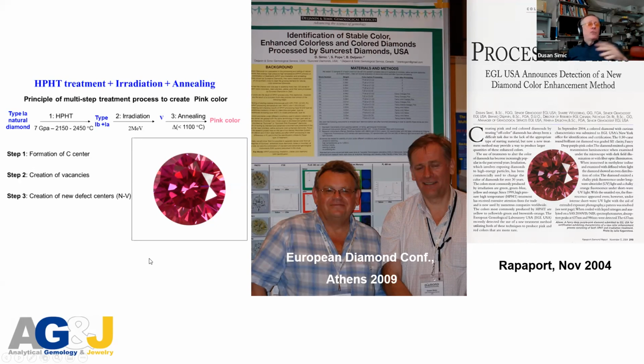I'm sure that you know all about this, but just to repeat first: you have to deassociate nitrogen to create single nitrogen. After that, make irradiation, and during the annealing, this single nitrogen will be bonded with a vacancy, and this bond is creating a pink color. Of course, you have to create enough vacancies in order to make light or intense pink color.